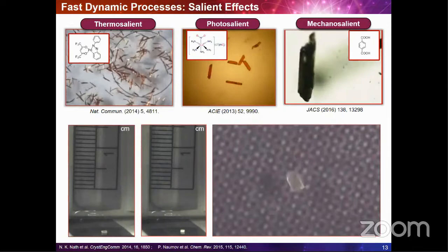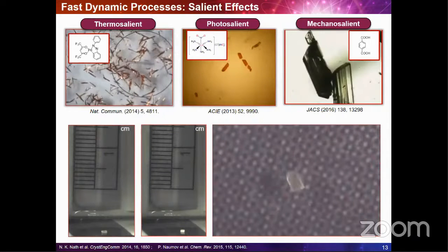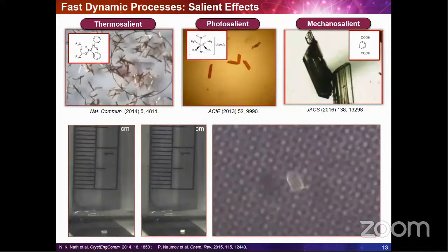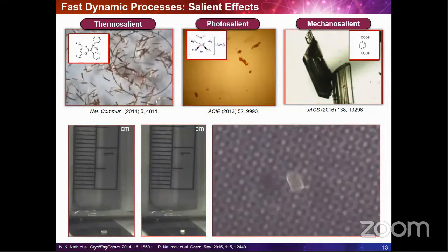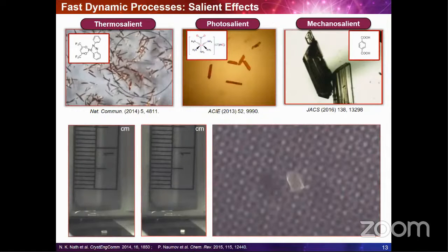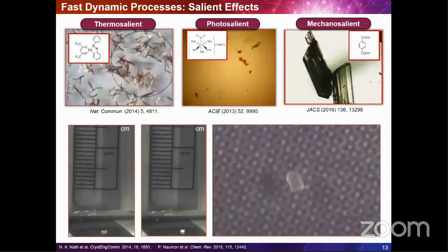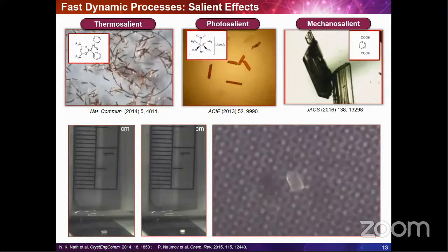These are three subclasses of dynamic materials which undergo cooperative martensitic transitions, and this results in rapid release of elastic energy and is manifested as motion across distances, and these distances can vary from several millimeters to a couple of meters. It has also been demonstrated that the phase transitions that underlie these thermosalient crystals are exceedingly fast, and they're actually much faster than the other more common solid-solid transitions. So if we combine this property with the easily detectable and measurable crystal expansion or contraction on a macroscopic scale, this makes a distinct property for thermosalient solids and favors these molecular crystals as controllable, work-generating elements that could be implemented as an active part of actuating systems or devices.